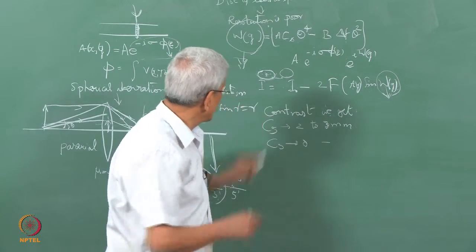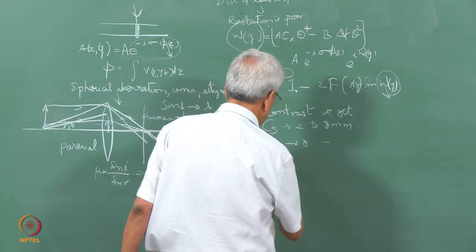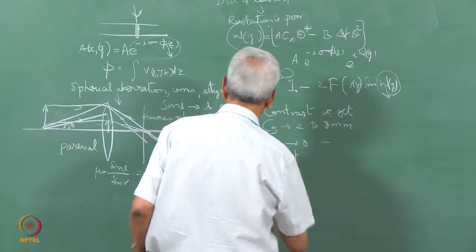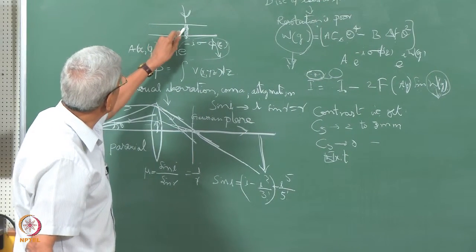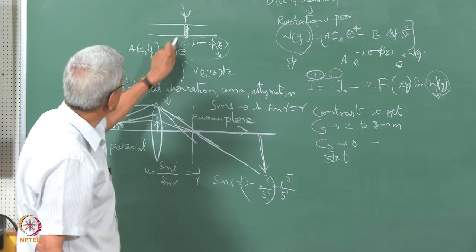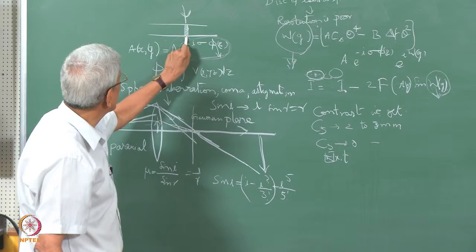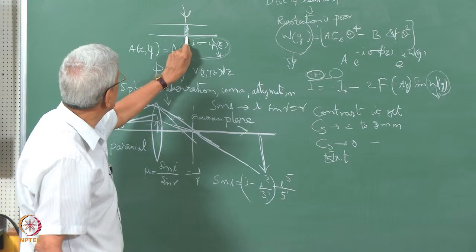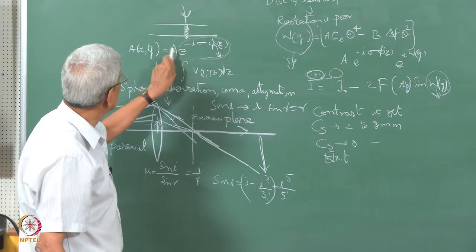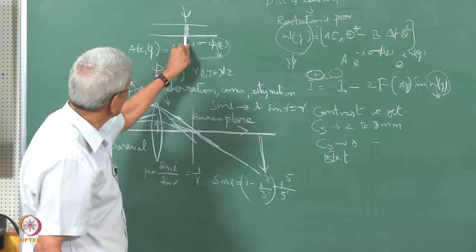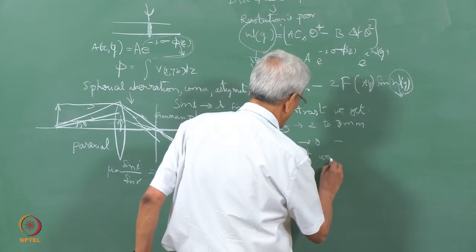Using these images we could get the exit wave function. As I mentioned here, as the electron beam enters and passes through, only the phase is modified. So, the wave as it comes out has a different phase compared to what it had when it initially entered, and this is called the exit wave.